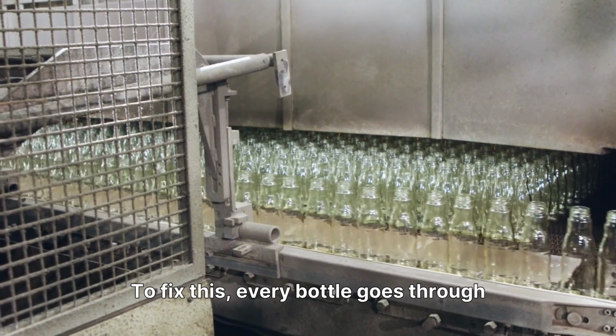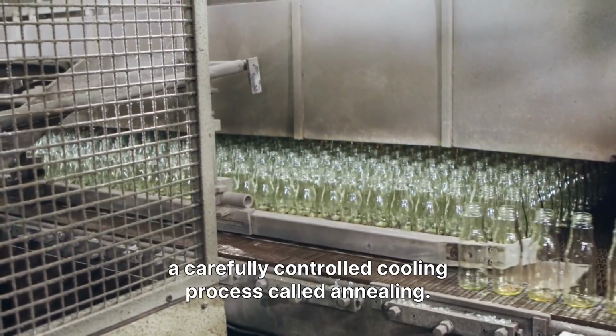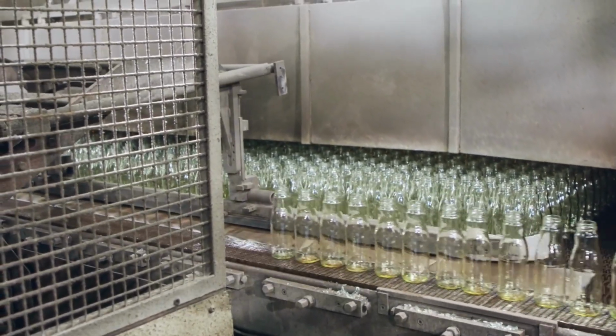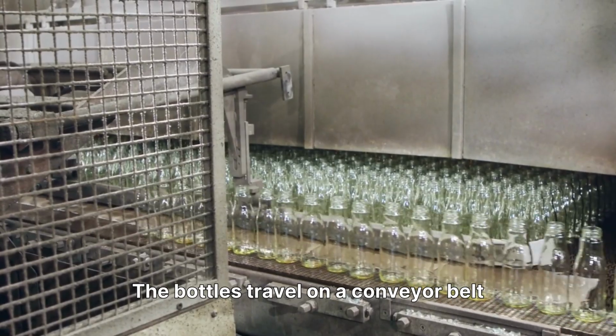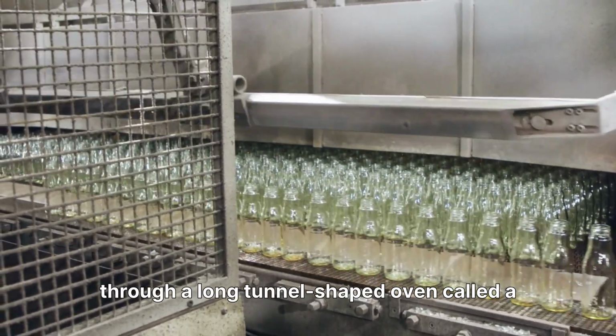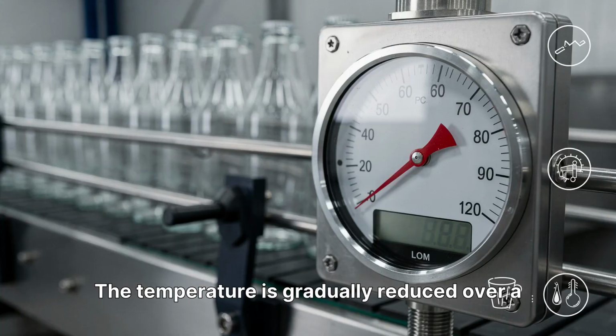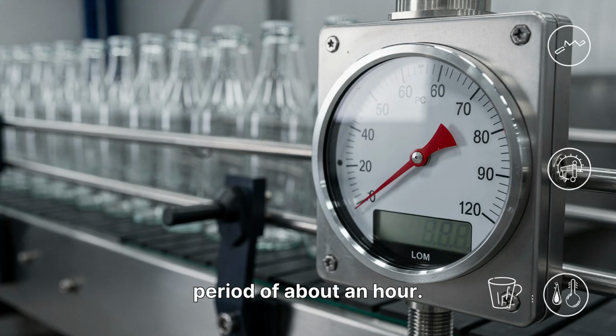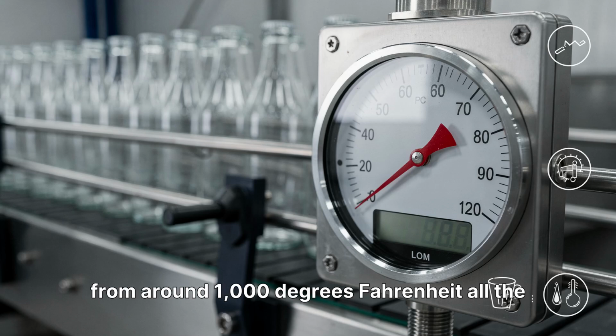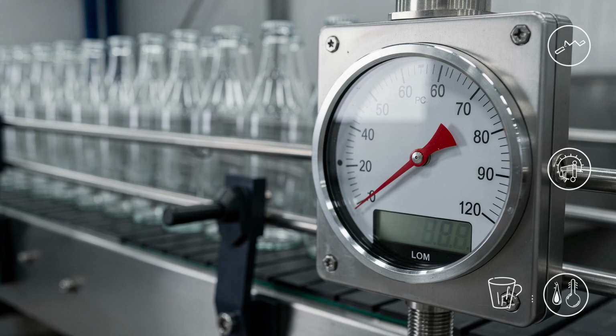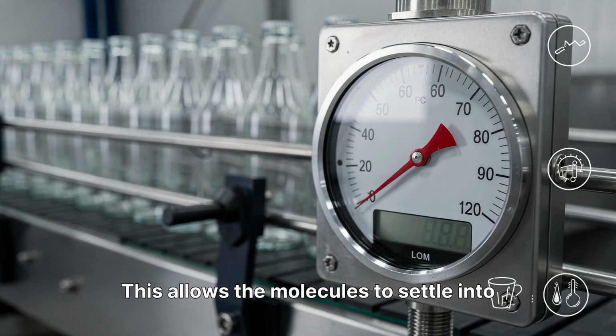To fix this, every bottle goes through a carefully controlled cooling process called annealing. The bottles travel on a conveyor belt through a long tunnel-shaped oven called a lehr. The temperature is gradually reduced over a period of about an hour. The glass is slowly and evenly cooled from around 1,000 degrees Fahrenheit all the way down to room temperature. This allows the molecules to settle into a uniform, stress-free arrangement.